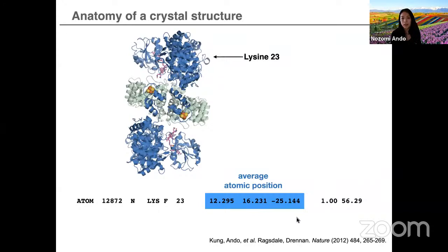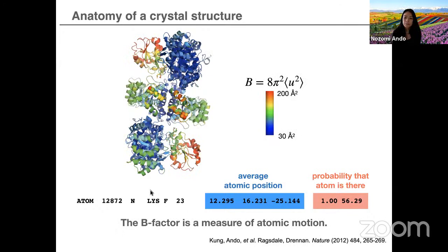And we have this impression that crystallography is giving us a static structure, a high resolution but a static structure. But it's already clear just from looking at a PDB file that molecules inside of a crystal are still moving just like they do in solution. And so this actually represents the average coordinate. And there are two other numbers that describe the probability that the atom is actually there. The first number is occupancy, which we often set to one if that atom is part of a molecule. And the second number is the so-called B factor, or the temperature factor. And this is a measure of atomic motion.